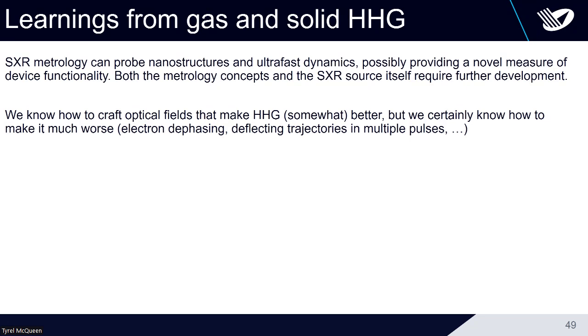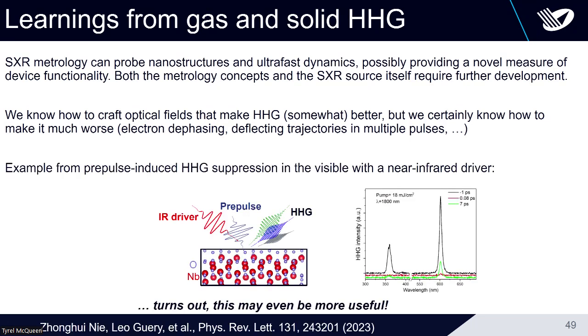So whenever you try to optimize something, usually you make it worse. And then it took us a while, but at some point we realized this is actually maybe even more useful to be able to make it worse. There's one example where we generate harmonics from niobium oxide, a correlated material. You add a pre-pulse and you get these spectra. It's really visible, low harmonics, third and fifth. You add a pre-pulse and you see you completely kill the emission if you do that.